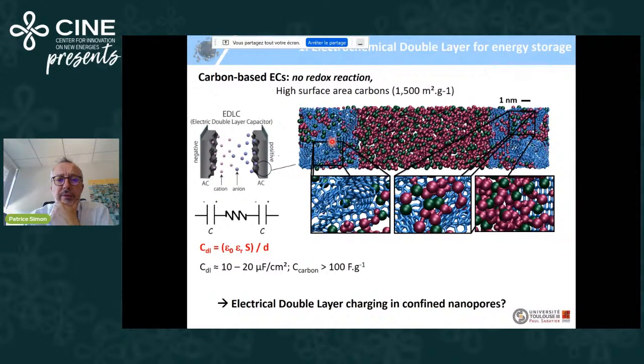You can see the porous carbon electrode, the second porous carbon electrode, the electrolyte with cations in red and anions in green. And when you polarize, ions enter the carbon pores and you store the charge electrostatically by charging the double layer capacitance. The double layer capacitance is proportional to the dielectric constant of the electrolyte, multiplied by the surface area of the porous carbon, the electrochemically active carbon-electrolyte surface area, divided by the approaching distance of the ion to the carbon surface.